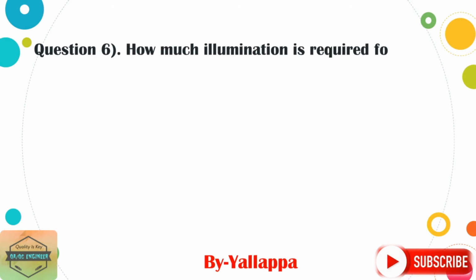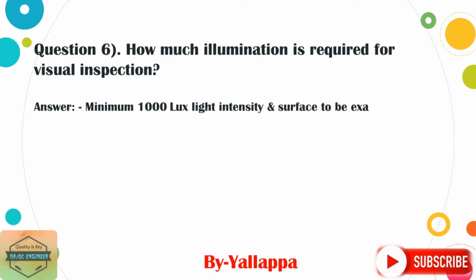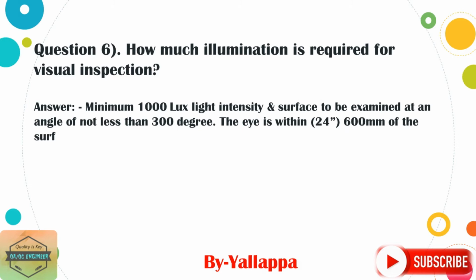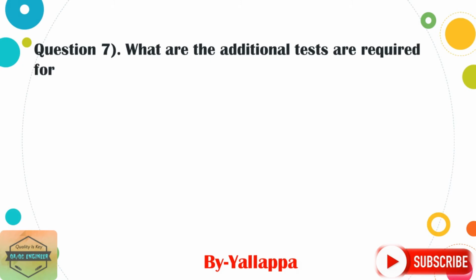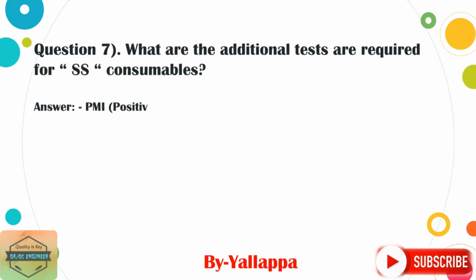Question 6. How much illumination is required for visual inspection? Answer. Minimum 1000 lux light intensity, and the surface is to be examined at an angle of not less than 30 degrees. The eye is within 24 inches, 600 millimeters, of the surface to be examined. Question 7. What additional tests are required for SS consumables? Answer. PMI, positive material identification.